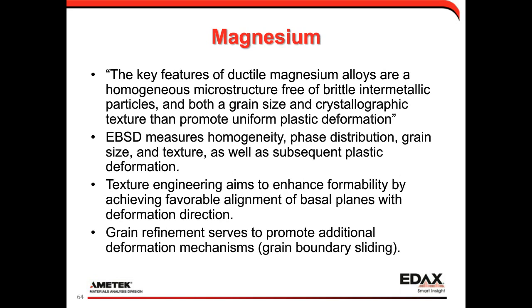And so what we want to do is use EBSD to measure the homogeneity, the phase distribution, the grain size, and the texture, as well as whatever plastic deformation and twinning occurs. Texture engineering will aim to improve formability by getting favorable alignment of the basal planes with the deformation direction. And then by refining the grain size, we can activate additional deformation mechanisms such as grain boundary sliding, which improves formability.